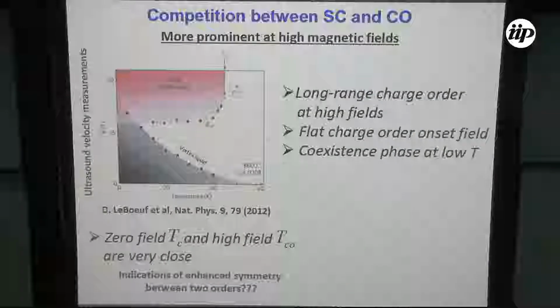So this competition is much more prominent if we put a high amount of magnetic field. So this is a magnetic field temperature phase diagram, which I have taken from ultrasound velocity measurements of David LeBoeuf's group. So what they did was that at low field, you can see that you have a vortex solid or a vortex liquid. You have superconductivity in the sample. But if you crank up the magnetic field, you will see that there is an onset field above which superconductivity gives way to charge order.